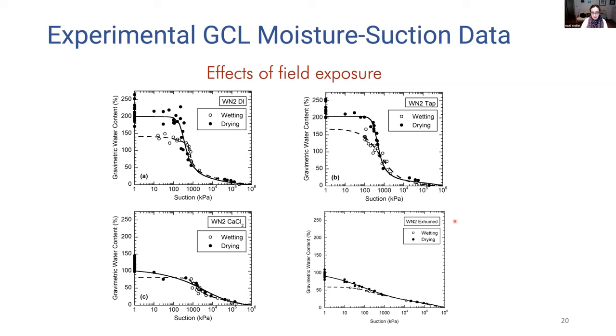And when we look at these four graphs all together, we see that again, the deionized water and tap water response are similar. We see the significant change when we switch from these solutions to the more chemically aggressive solution, the calcium chloride solution. The water content relationships collapse again. We do not have high water contents at saturation anymore. Hysteresis is essentially non-present in the system.